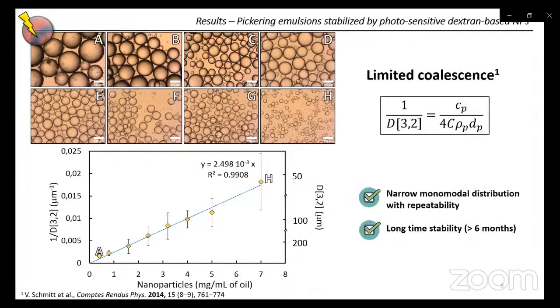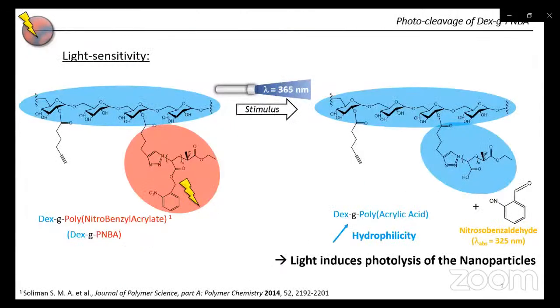This is known as the limited coalescence phenomenon, which is quite studied, and we obtained in a reproducible way narrow size droplets. But also, we observed that these emulsions are quite stable, as they are stable for more than 6 months. Then, as we grafted this photosensitive hydrophobic polymer, poly(nitrobenzyl acrylate), this photosensitivity can be described as the photolysis of the nitrobenzyl group, which produces an acrylic acid unit, but also nitrosobenzaldehyde. This change leads to a dramatic increase in the hydrophilicity of the whole chain, and at a higher scale, we can say that light induces the photolysis of the nanoparticles.